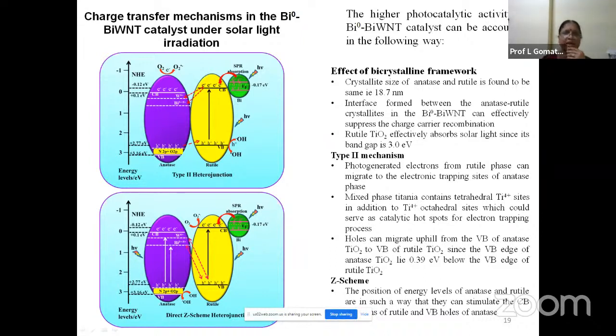Now here I have given two figures. The two oval-shaped circles, violet and yellow, represent TiO2. One is in the anatase phase, the other in the rutile phase. Both figures represent only the BI0 BIWNT catalyst sample. For the first, we can take up the bicrystalline framework. Bicrystalline is anatase and rutile. We can observe that both crystallites have almost similar crystallite size, 18.7 nanometers. The interface formed between anatase and rutile can effectively suppress charge carrier recombination, as shown in the figure.